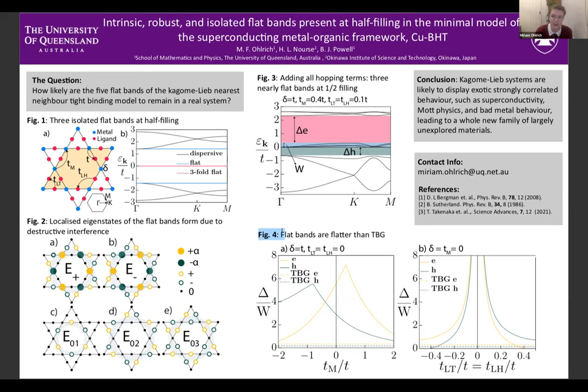Now, you can see this in figure four, where I've plotted the band gaps on either side of the central bands normalized over bandwidth. And as you can see, the band gap to bandwidth ratio for the Kagome-Lieb tight binding model is larger than that of twisted bilayer graphene for a similar model for a significantly broader range of hoppings than is likely to be seen in a real material. So because of this, the Kagome-Lieb lattice is likely to display fun, strongly correlated behavior, such as superconductivity, leading us to a whole new family of unexplored materials.